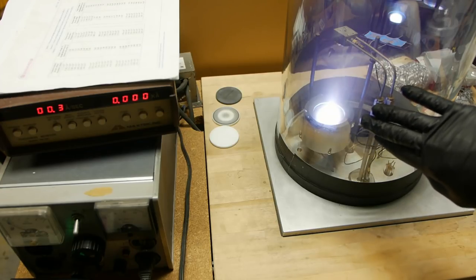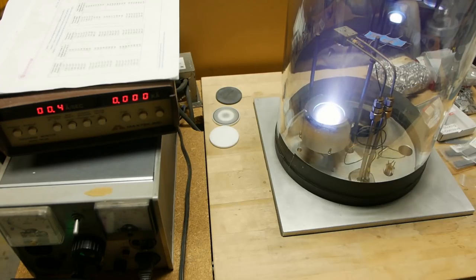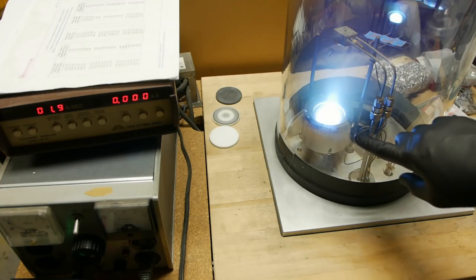We're running at about 110 watts. 550 volts at about 200 milliamps. And now you can see the color is really green. And over here, we've got two angstroms per second. Should go a little bit higher than that once it's fully running.